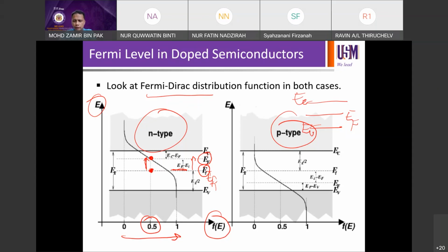On the other hand, if you are incorporating more boron or aluminum or gallium into the silicon, you're introducing more and more holes into the silicon. And now let's look at the center point again. Now it changes from the center, right in the middle of your band gap, downwards, closer and closer to the EV, to denote formation of P-type.